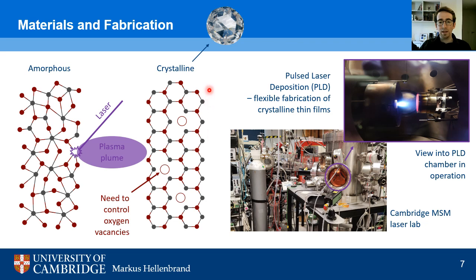Now, it is very difficult to make a perfect crystal. So typically there will be what we call defects in a crystal. The materials that we're looking into are mostly oxides. That means combinations of some material and oxygen. So in this example, oxygen would be the red one, and the other material, whatever it may be, are the gray circles. And one of the most common defects in oxides are so-called oxygen vacancies.